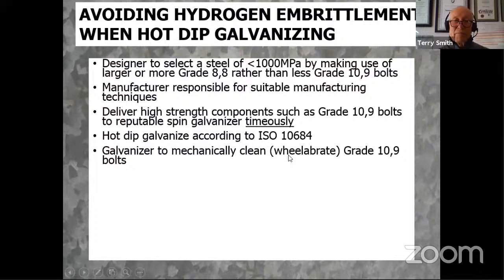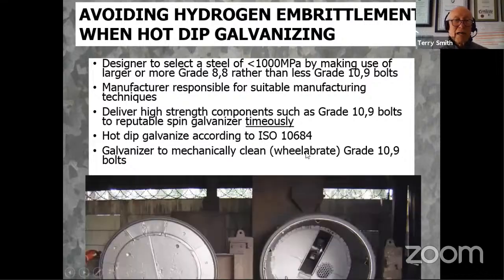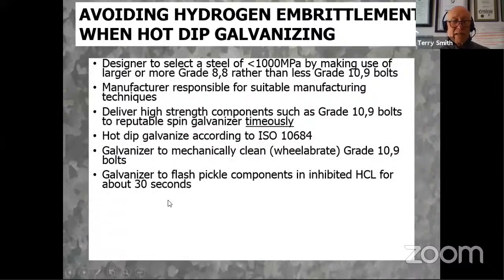Galvanize and mechanically clean. Wheel abrade grade 10.9 bolts. As you can see, this is the wheel abrasion machine here. Then the galvanizer should flash pickle components in inhibited hydrochloric acid for about 30 seconds.